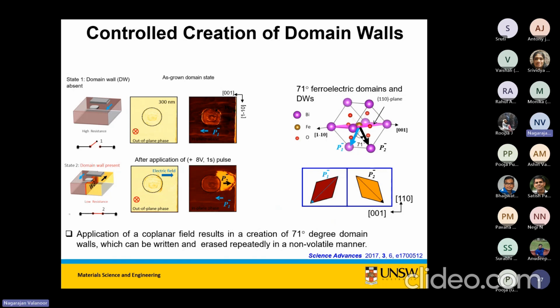The moment we apply a bias on top of the electrode, there's a 300 nanometer electrode that is sitting up here. You can then create switching, a correlated switching, where it creates a domain wall, and you see that arrowhead kind of shape of a domain wall that is created. And that domain wall is going from that small electrode, it is going all the way to that big giant electrode. What happens if that wall is conducting?